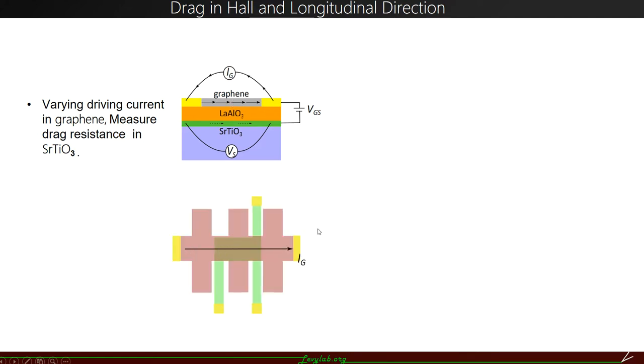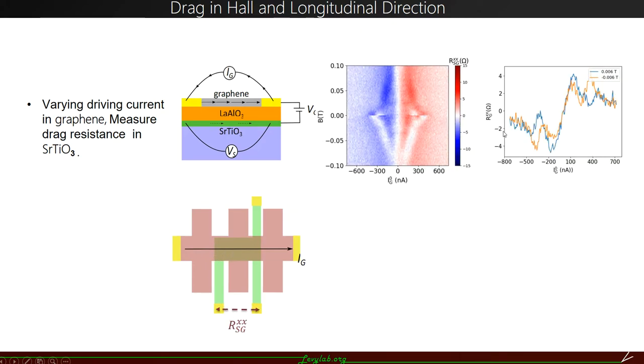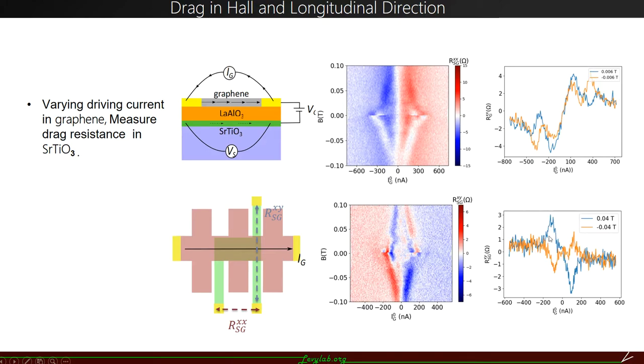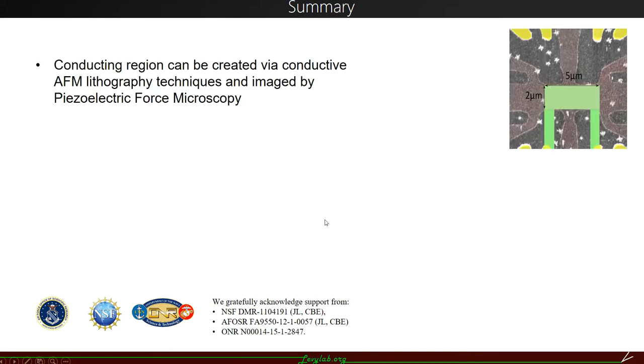The current we measured in graphene. So we're running the current in graphene and measure the drag voltage in two directions. One is parallel to the driving current. We can see the drag signal is almost symmetric under a positive and negative magnetic field. And if we measure the drag voltage in a direction perpendicular to the drive current, the drag signal is antisymmetric under magnetic field.